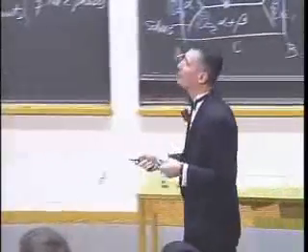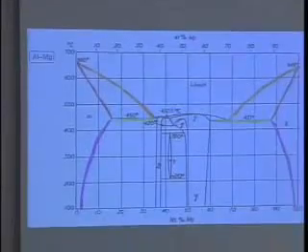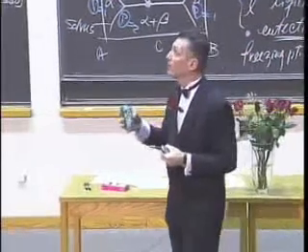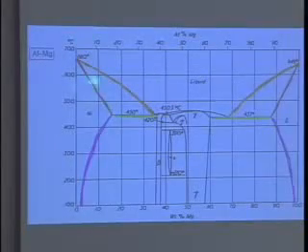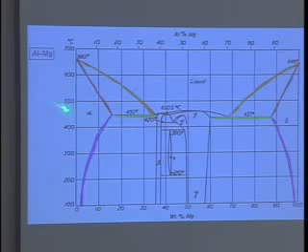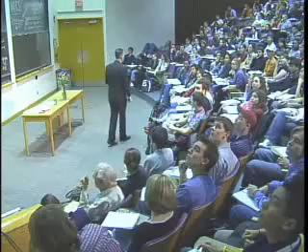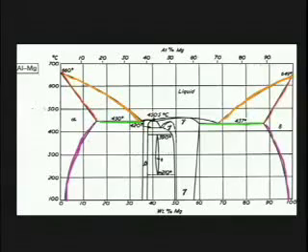This is really fantastic stuff. Oh, here's a good one, aluminum magnesium. This is the beverage can. So we're looking at a eutectic system. We're going to add a few percent of magnesium into aluminum, which is going to put us here, in the alpha solid solution. If we add too much, we end up in a two-phase regime. And that's no good, because when we go to deform the can, the metal will tear, so we have to have single phase.